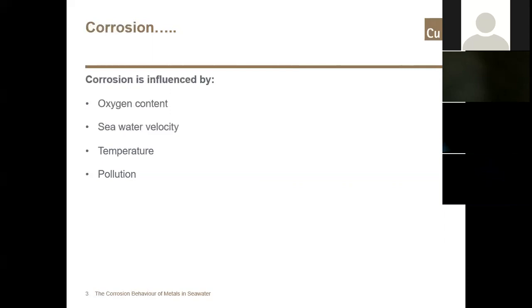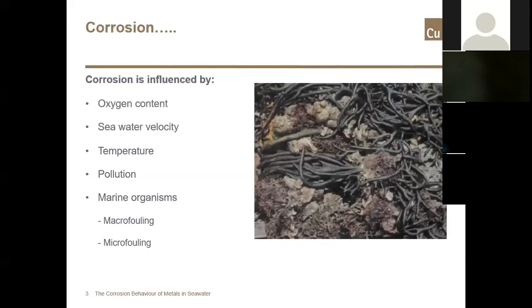And also many metals can be subject to the attachment of organisms in the form of both micro and macro fouling. You can see from the example on screen that this can completely cover the surface of the metal, so we cannot even see what's underneath, and worse still, we can't see if there are any issues with corrosion in the local area. These variables are not straightforward, and not only will seawater vary from location to location, but individual places can show changes in temperature, biological activities, etc. during different seasons. So the complex nature of seawater makes it difficult to achieve realistic performance data from short-term testing in synthetic waters.